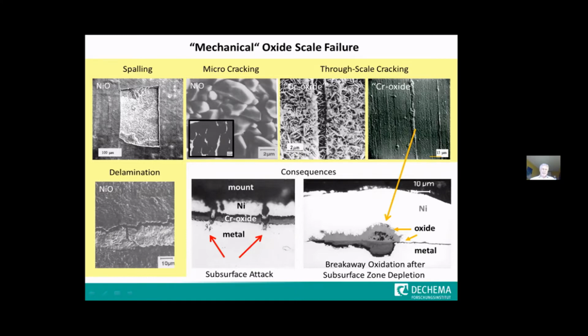This is a very simple case with a very simple oxide. Let's call it a model oxide, which is nickel oxide on nickel. And you see what can happen if stresses damage these oxide scales. Complete flakes can break out of the surface of the scale and can fall off, so that the metallic material is again exposed to the corrosive environment. That can be the beginning of the end of life, and increased corrosive attack can start with such weak points of the surface.